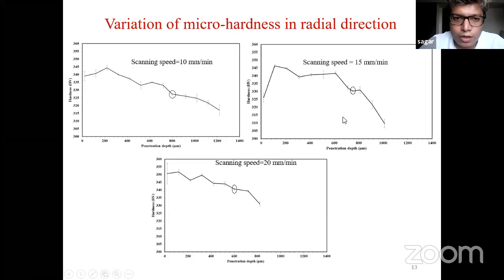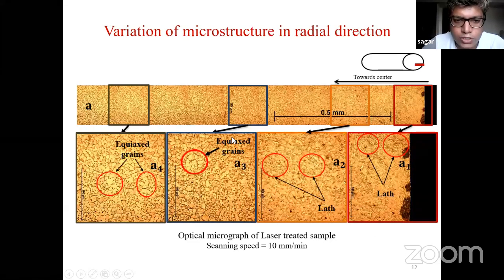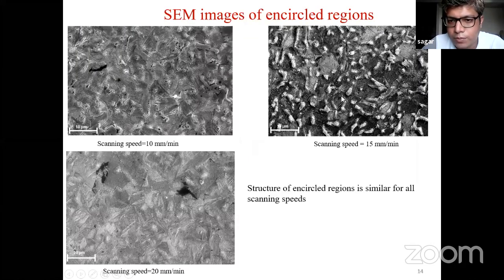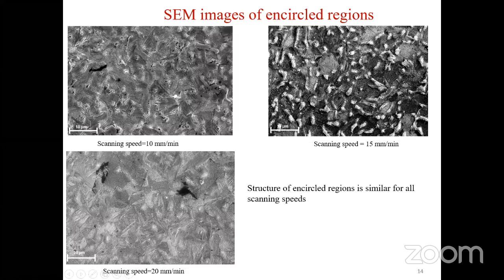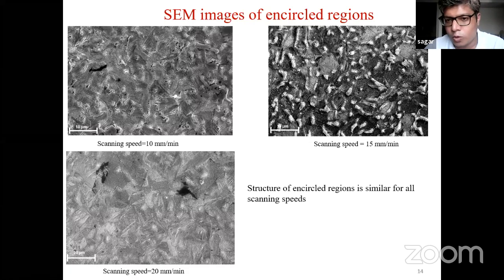Initially the laser treatment affects the whole grain structure, but when it goes near to the base material, it affects only the grain boundaries, because the grain boundaries are the weakest section inside the grain structure. That's why they have very high energy to shift. These grain boundaries will try to go into the stabilized phase, but since the laser treatment is not allowing the time to go into the stabilized state, it has been restricted right there.